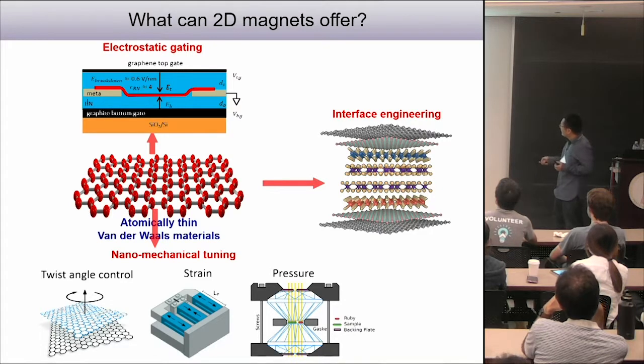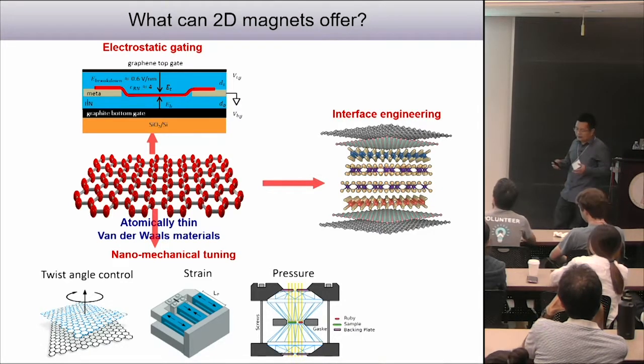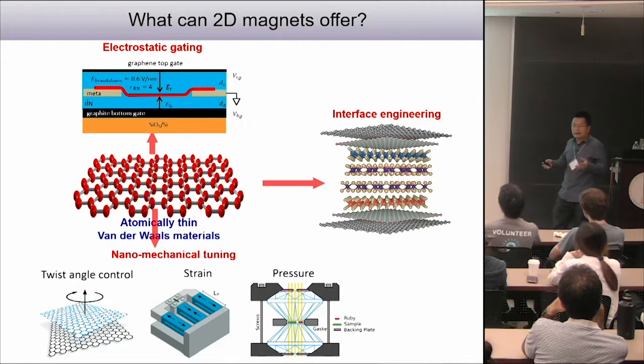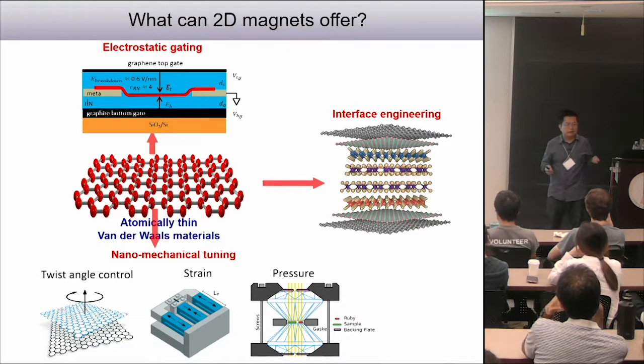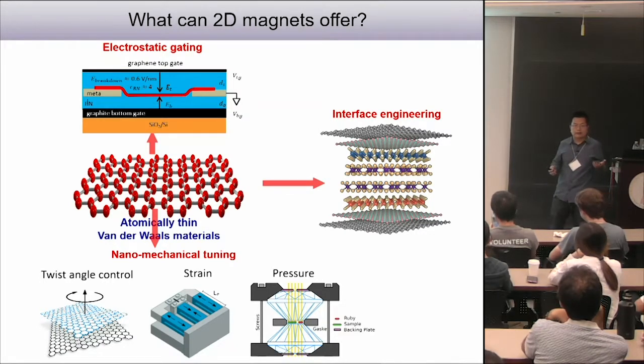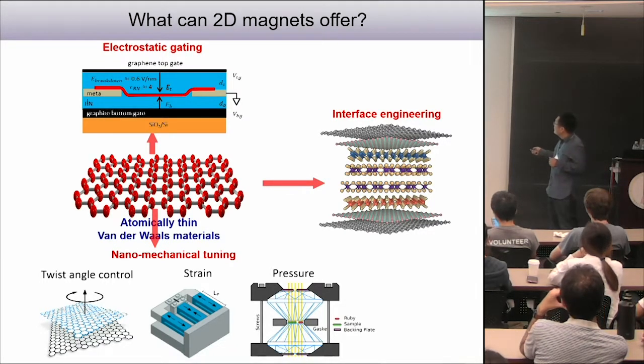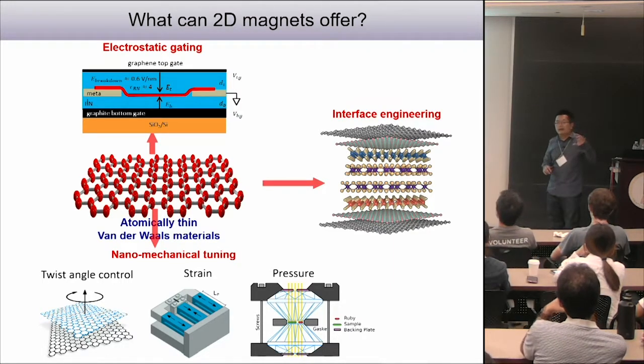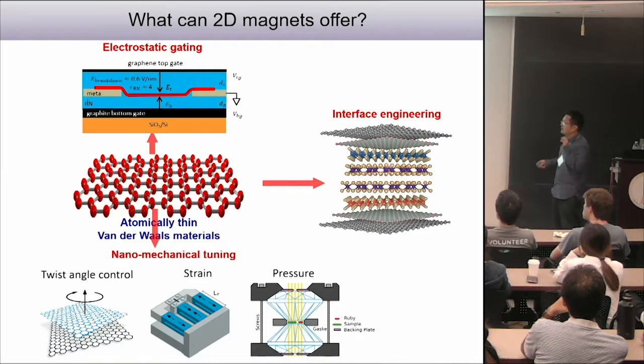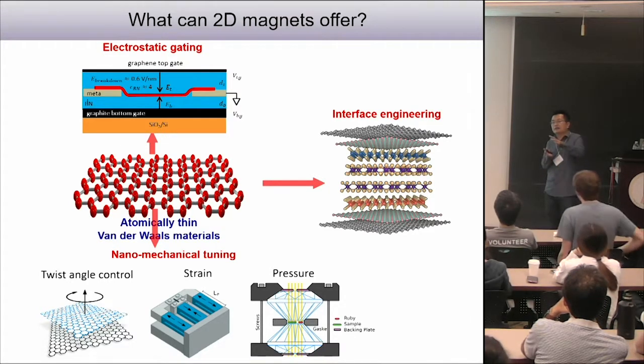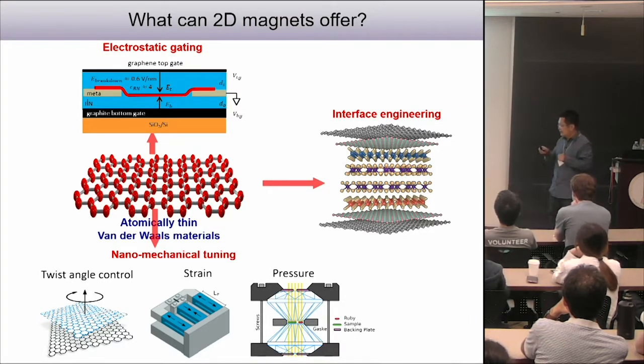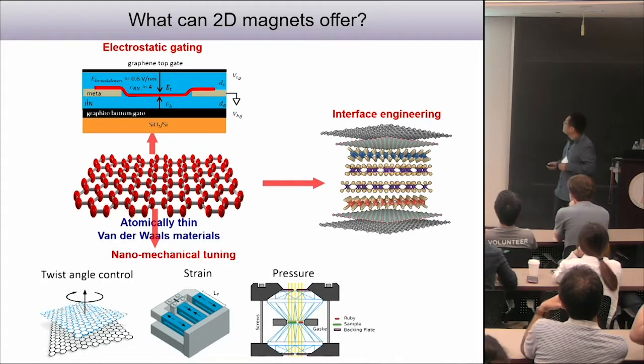And the other very powerful technique we're trying right now is pressure. So we know pressure actually is a useful technique to, for example, get high temperature superconductivity, right? But for 2D materials, it's a van der Waals structure, so interlayer coupling actually is critical. And then the pressure actually is a very useful technique to control this interlayer coupling, right? For example, by controlling the interlayer separations or just controlling the layer stacking arrangement. Okay, so I'm gonna show you an example today.